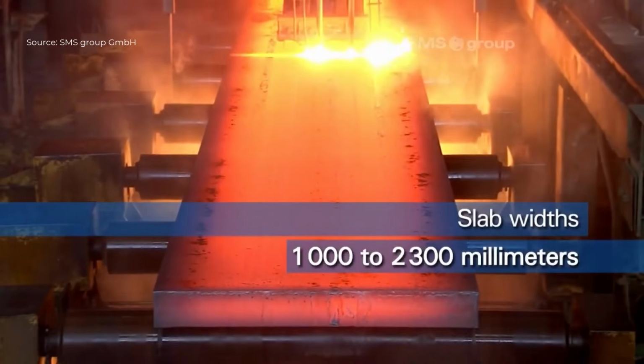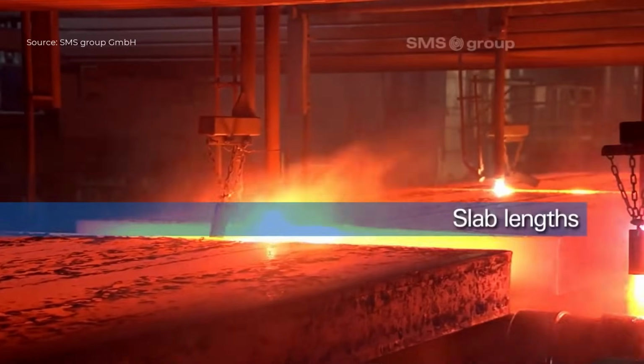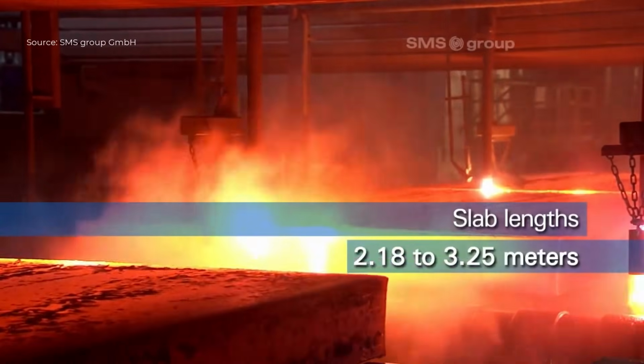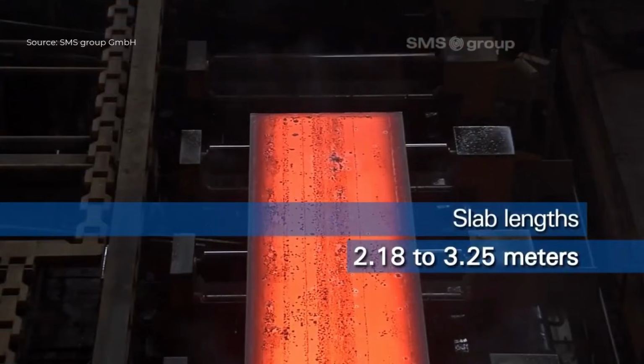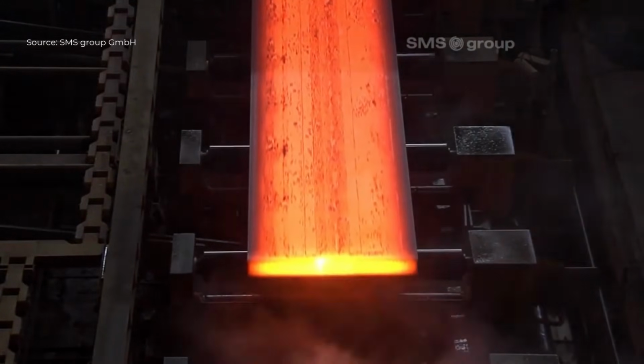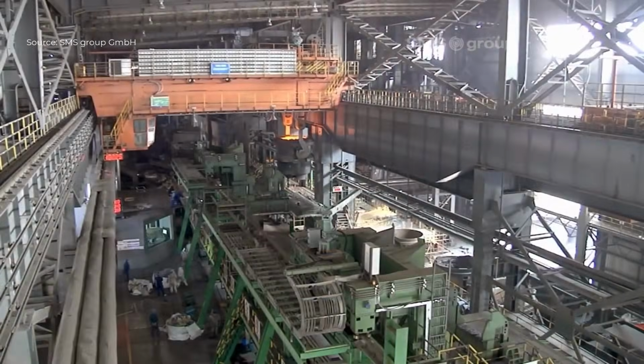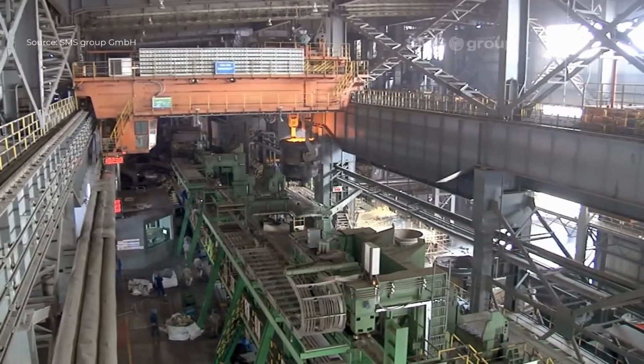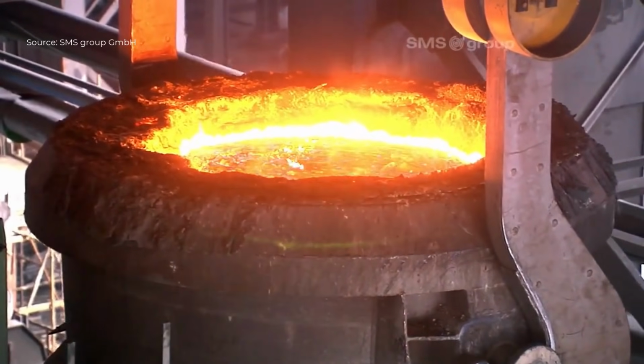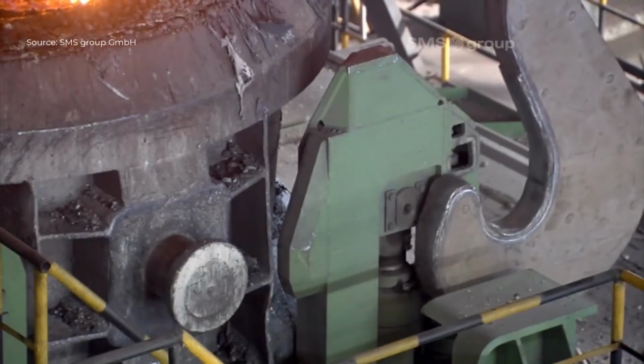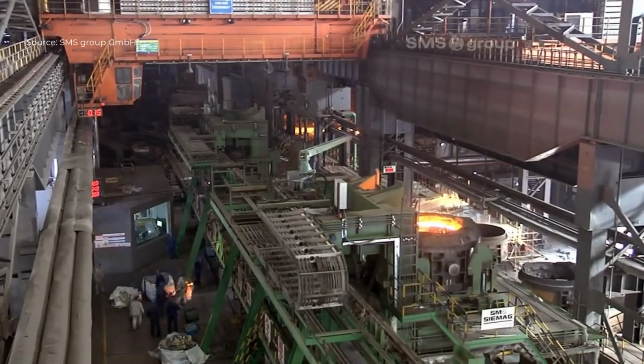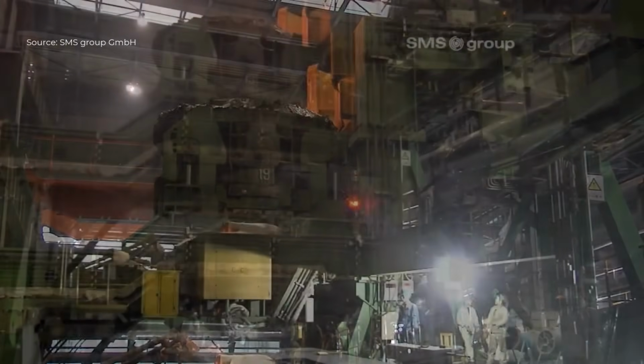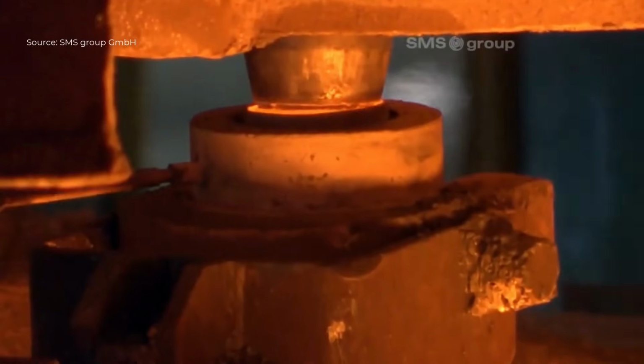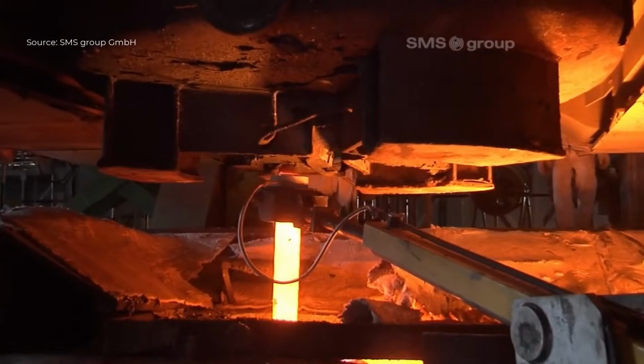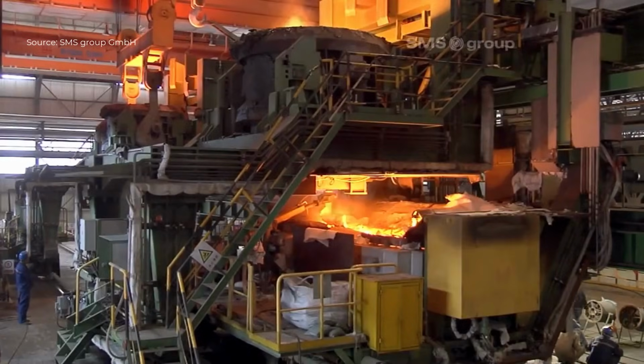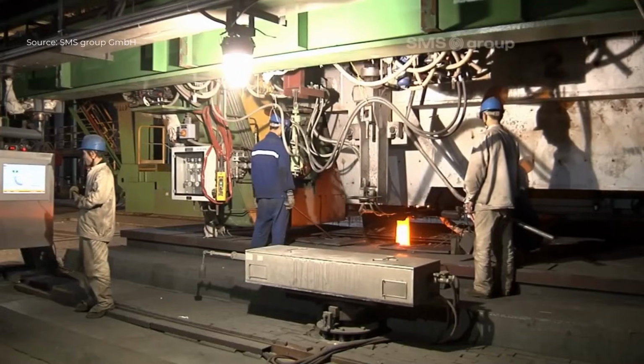During continuous casting, the solidification process is closely monitored and regulated by advanced technological control systems. Process models such as dynamic solidification control and dynamic soft reduction are applied to compensate for shrinkage during final solidification. These functions reduce center segregation and internal porosity, resulting in slabs with improved density and consistent mechanical properties. Continuous mold and strand monitoring allows real-time adjustments to casting parameters, ensuring stable operation throughout the sequence.